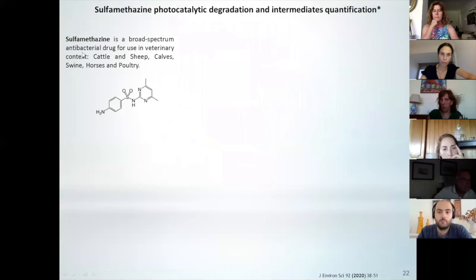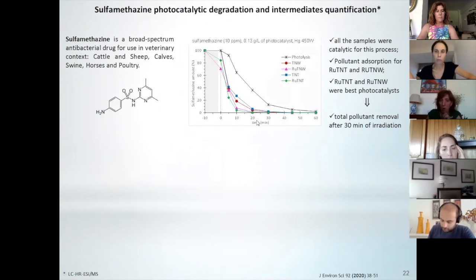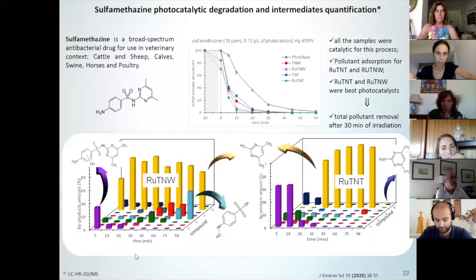We decided also to investigate these catalysts for the sulfamethazine degradation. In this case, the difference between the ruthenium titanate nanotubes or nanowires is not so obvious. The system is very fast. After 30 minutes, I have no sulfamethazine in solution. But once again, when we compare the profile of degradation and formation of the byproducts, we can see that we have very different performances. For instance, after 90 minutes, I must remind you that sulfamethazine is degraded after 30 minutes. We need one more hour to have no byproducts when we use the nanotubes. And for this, we need more time to degrade these byproducts.